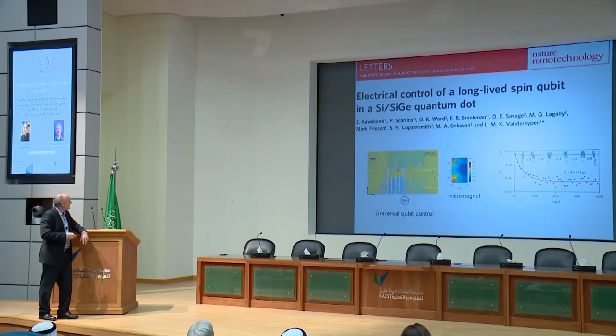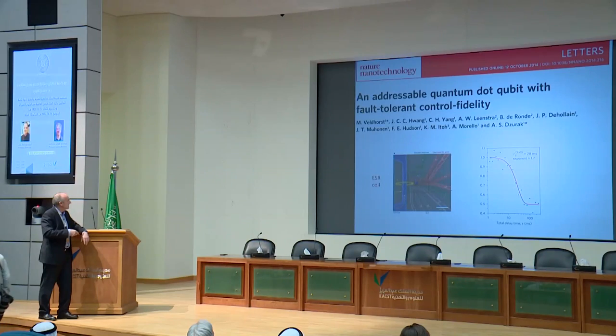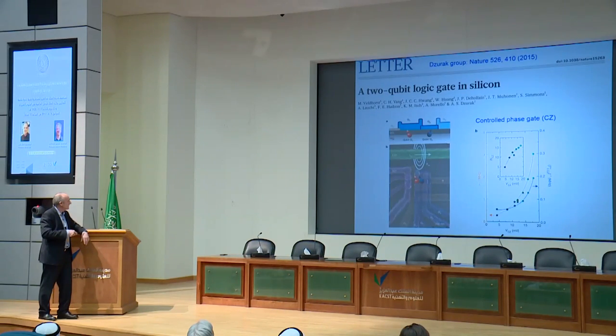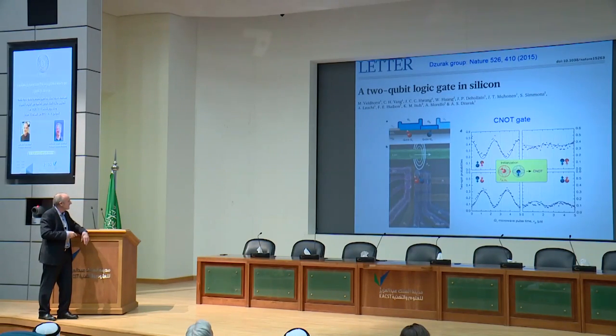And there are now a number of labs, which I just flashed now, using similar materials where you can use holes and even avoid the nuclear spins, like silicon, silicon germanium quantum dots. Again, these are the groups I mentioned before, so they have shown here single spin rotations and controlled phase gates. So that's the 2-qubit entanglement gate shown in this material, so in silicon.